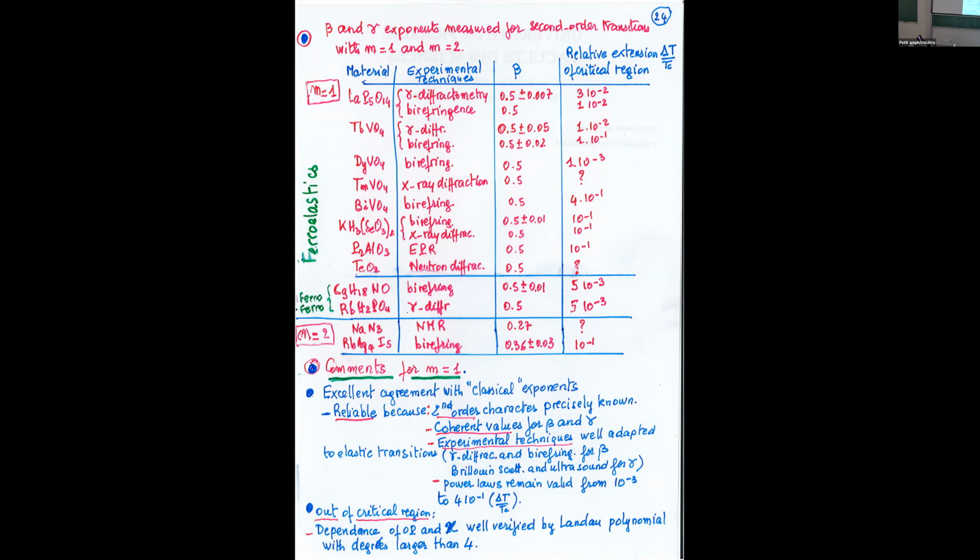But of course, anti-ferroelectricity is very difficult to evidence experimentally. It's only some macroscopic thing which defines anti-ferroelectricity, for example, a double hysteresis loop and things like that. But at the microscopic level, you cannot see the dipole. You can see the spins because of neutron diffraction, but you cannot see the dipoles. So there's always some struggling between people to say, is it anti-ferroelectric or not?